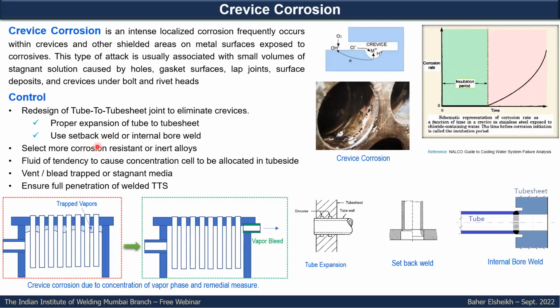To close the crevice or to eliminate this crevice corrosion, you need to think about the proper expansion of the tube to tube sheet so that you can close the crevice, or you might think about using a setback weld to expansion, or you might think about the internal bore if it can be applied. And you might select a more resistant material, so the condition is there but the material has higher resistance, or maintain the condition of the fluid itself to somehow reduce the tendency to cause corrosion. And in some heat exchanger designs, you might have vapor bleeding to avoid the stagnation of trapped vapors.